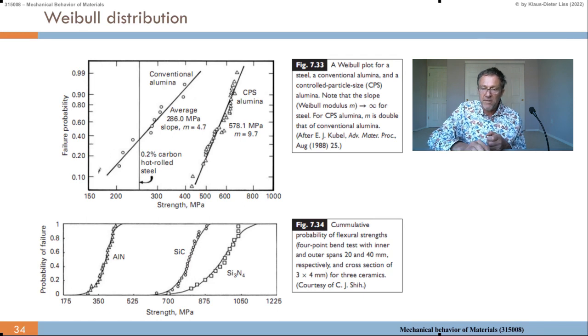Or here at the bottom, what we have there, cumulative probability of flexural strength, 4-point bend test with inner span, for 3 ceramics. So we have 3 ceramics, aluminium nitride, silicon carbide, and silicon nitride. And we see aluminium nitride has a very steep curve here. That means the M is large and it's relatively predictable. So that means the sigma critical is somewhere here, 60%, yeah. And it's relatively predictable. You see it starts here at 175, not at 0.